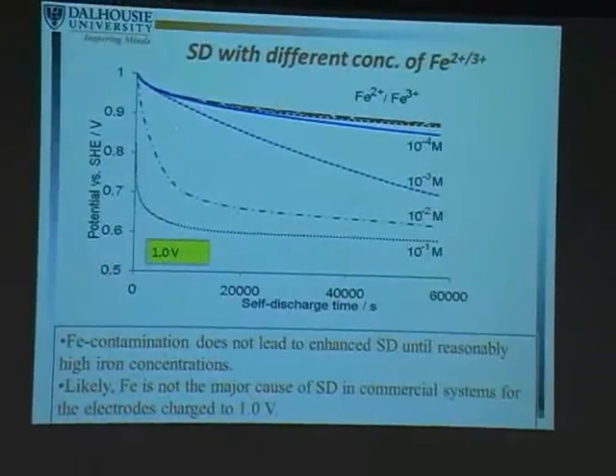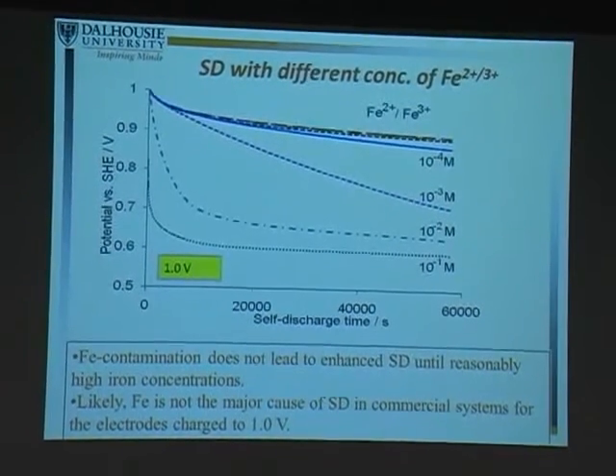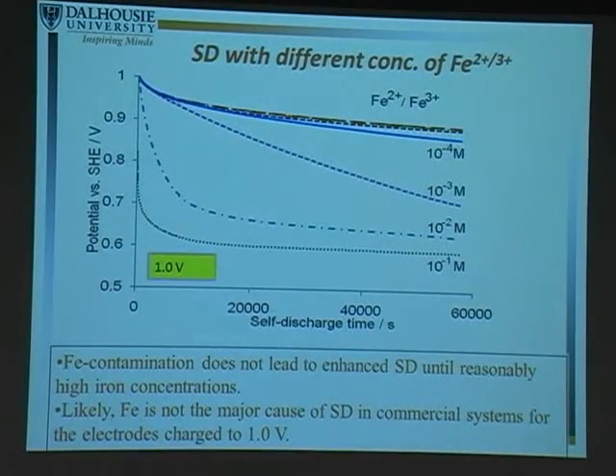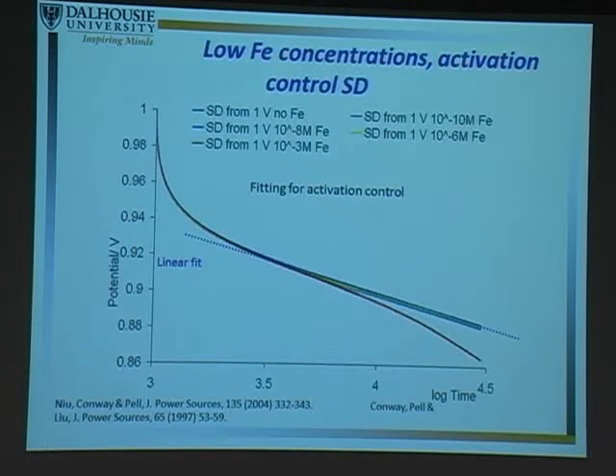If we continue to contaminate, because we like to push things, we see that at 10 to the minus 3, we absolutely start seeing self-discharge. At 10 to the minus 2 and 10 to the minus 1 molar, you're essentially discharging your electrode completely with these iron systems. Now, this is all the positive electrode, and I'm going to talk about the negative electrode as well.